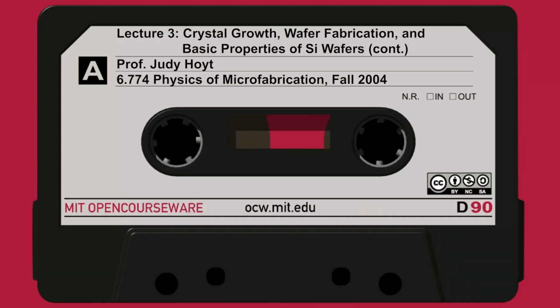And certainly this can happen. People believe it costs a fair amount of energy. That is, it's somewhat hard to do because you have to break all 4 bonds, because you're in the bulk of the crystal. Remember, in silicon, every silicon atom is 4-fold coordinated. It has 4 nearest neighbors with covalent bonding. Obviously, the Frenkel process is going to create 1 interstitial for every vacancy. So if Frenkel were the only mechanism by which we could create point defects, then C sub I would be equal to C sub V in equilibrium. But it turns out that's not the case.